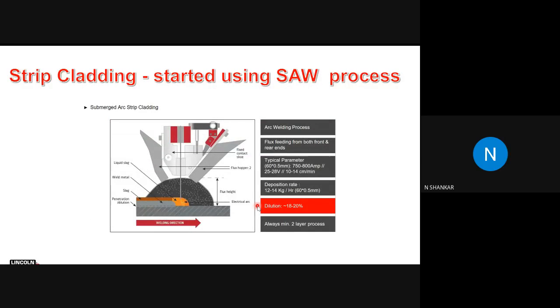Now we look at strip cladding using the submerged arc process. You need to have fluxes on both sides, fed from the front side and the rear side. The typical parameters are 750 to 800 amps, 25 to 28 volts, and a travel speed of around 100 to 140 mm per minute. That's the speed you can go. The deposition rate is usually about 12 to 14 kilograms per hour. Dilution, which is very important, is 18 to 20%, and you'll always have a minimum of 2 layers.